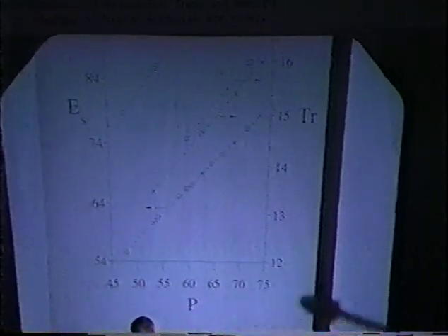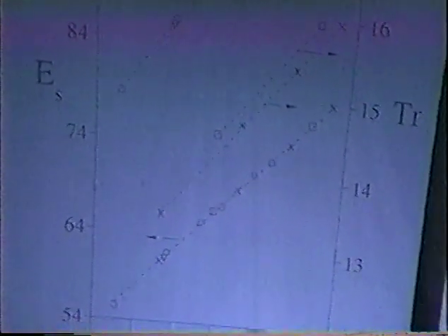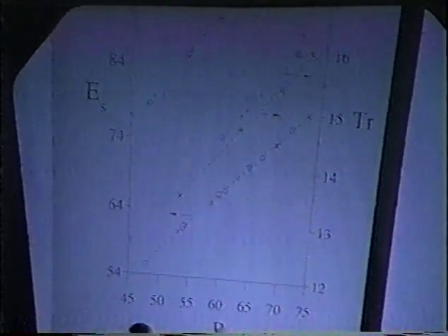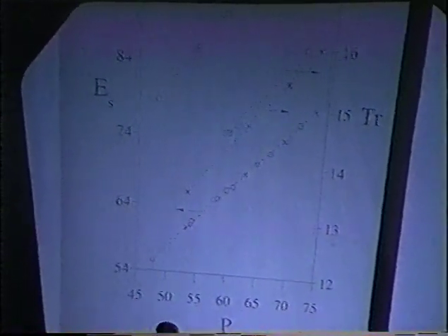You notice that even though I have 4 different gases here, I have one curve, one straight line. The open circles are argon at 1 atmosphere. The crosses represent helium at 4/10 of an atmosphere. The squares are deuterium at 0.2 atmosphere. And these triangles, of which there are only 2, represent admissions of a very small amount of air into the deuterium, and they also lie on the same line.